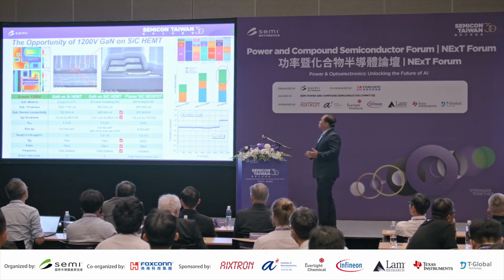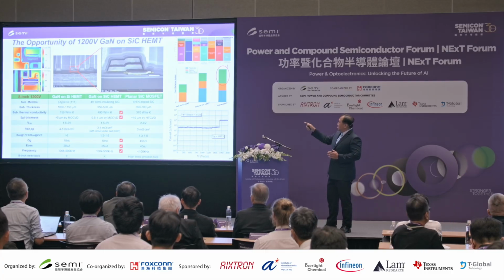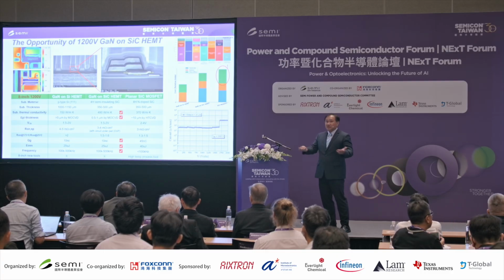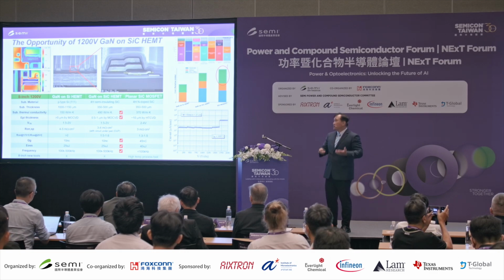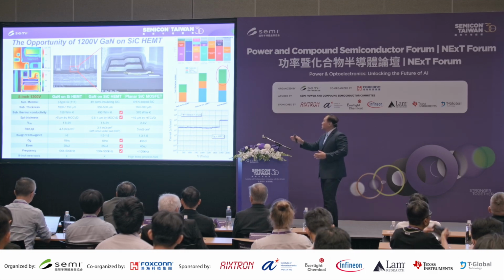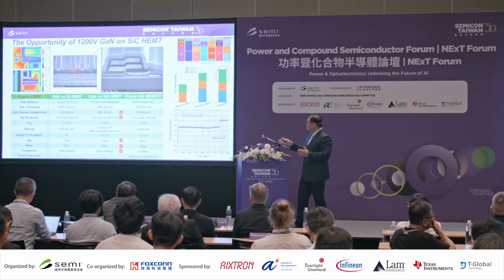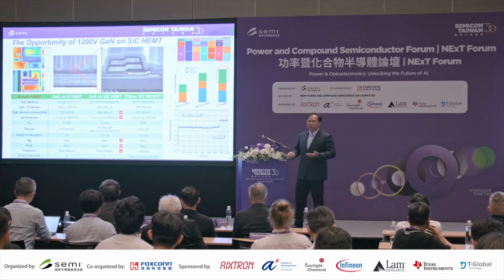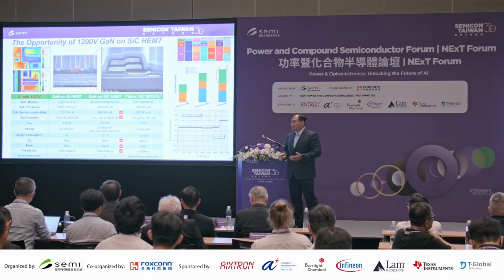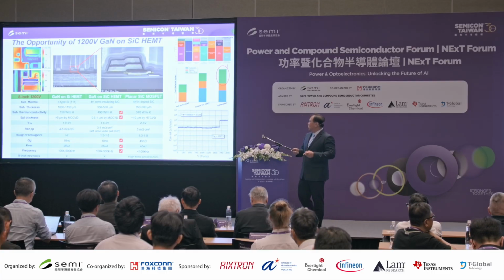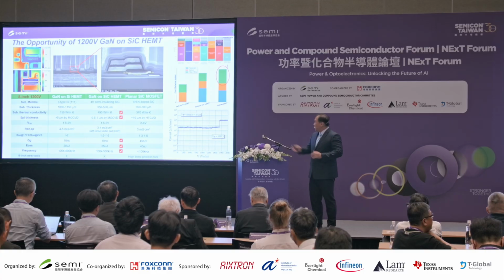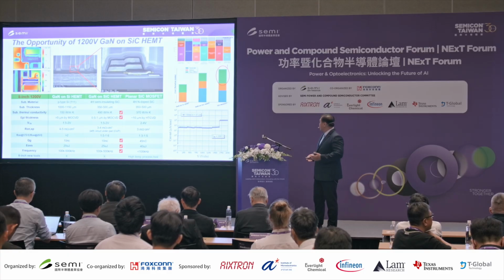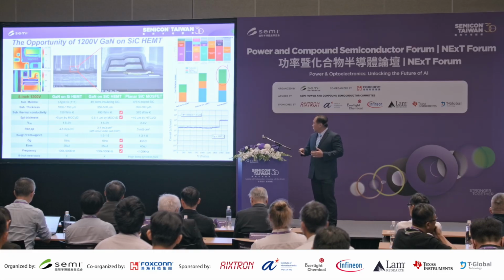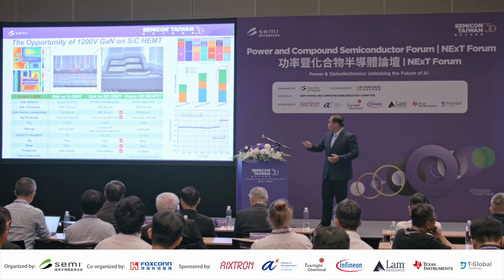Okay, so the opportunity of the 1200 volt GaN on silicon carbide HEMT, maybe we don't have to compare to GaN on silicon because I just told you the thick buffer and the poor thermal issue. But how about comparing the GaN on silicon carbide HEMT to planar silicon carbide MOS? Okay, be honest, based on the phonon scattering, the semi-insulating silicon carbide can really reach almost 500 watt per meter K, but this value for N-type is only 370, and for epi thickness is less than 1 micron, but for HTCVD more than 1200 volt, you need to grow by HTCVD 10 micron silicon carbide.